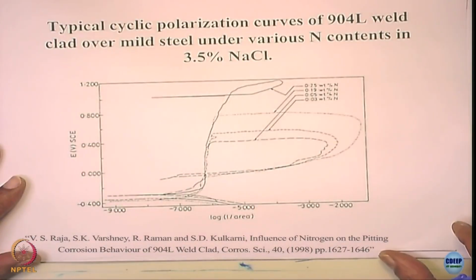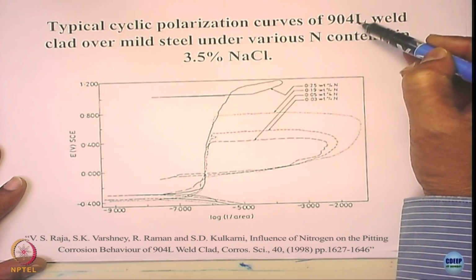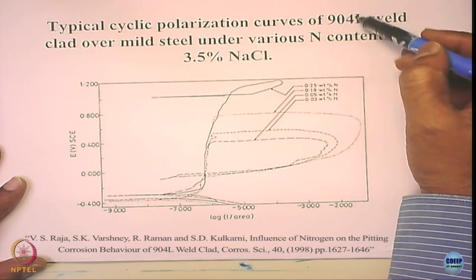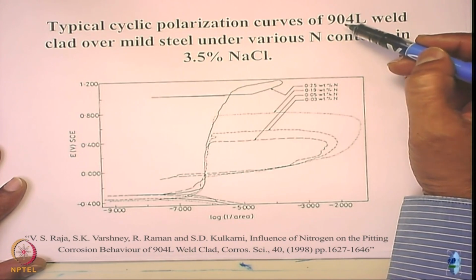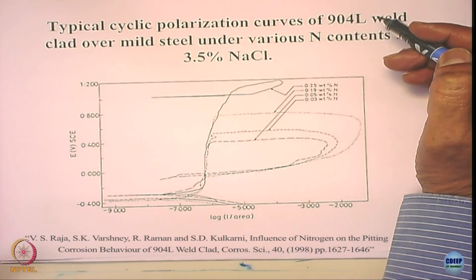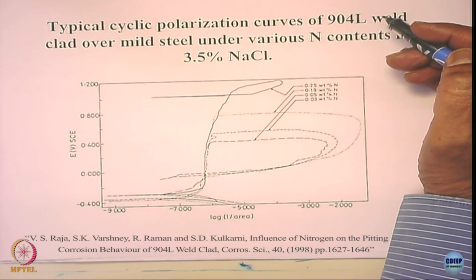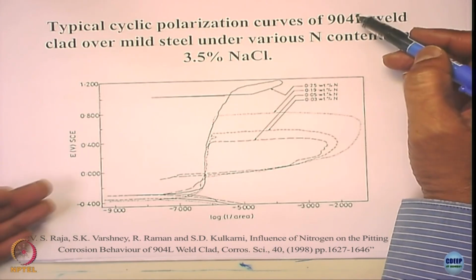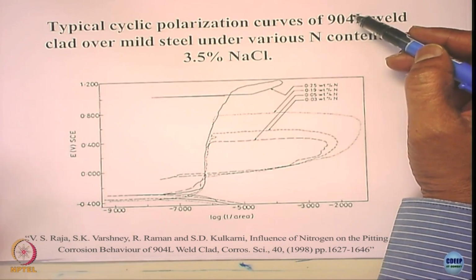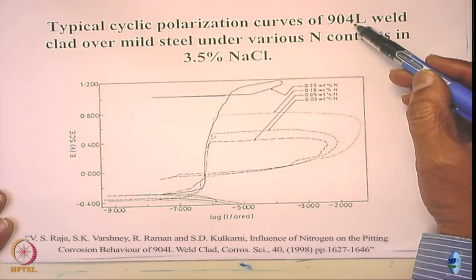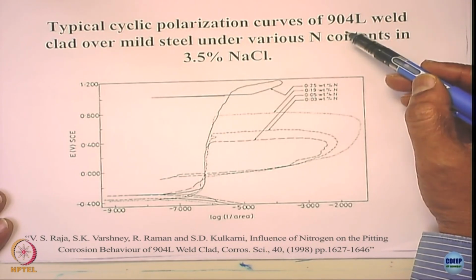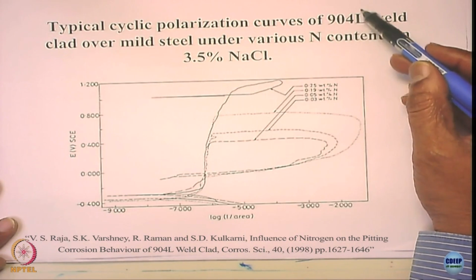Let me just see if I can show you some kind of curves here. Let me show this polarization curve, okay, and you see it is essentially a 904L filler wire, you know what is called a cladding, right? What is a cladding? You melt and deposit. You can also deposit without melting. It's a layer of, in this case, 904L formed on mild steel here, okay. This is done by welding, by weld cladding. So melt it and apply on the mild steel, and it's 904L, okay.